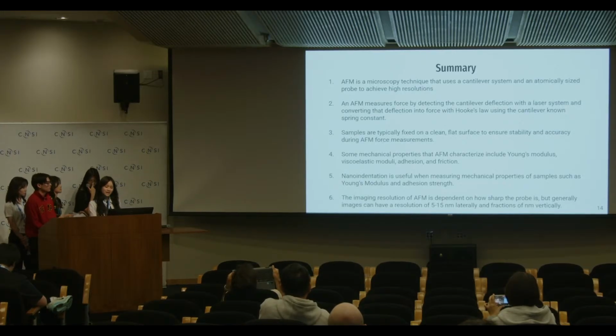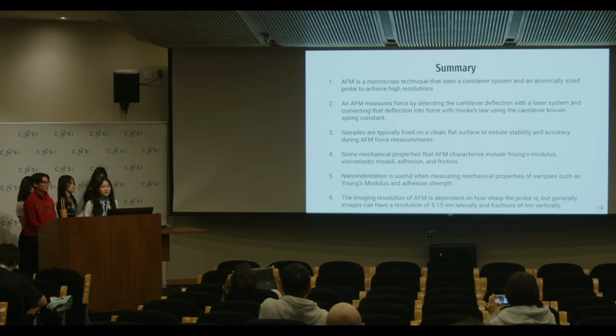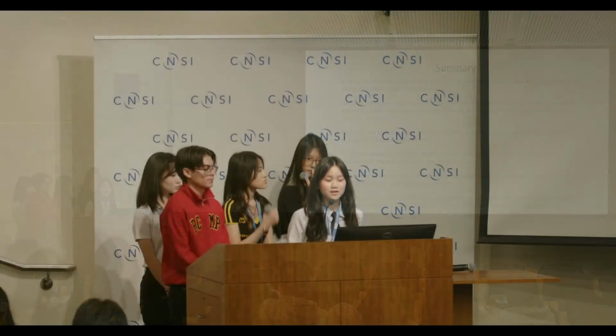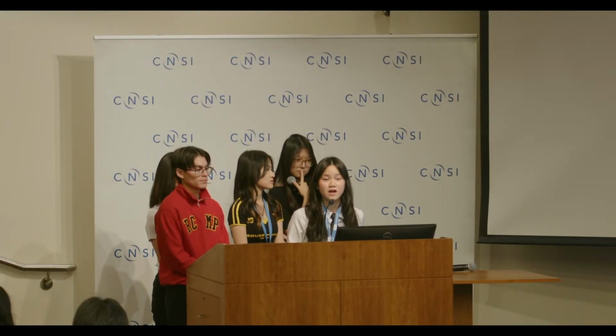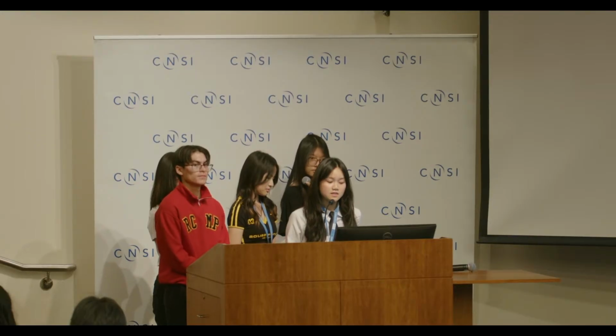This is a summary of everything we talked about today. First up is what AFM is, which is a microscopy technique that uses a cantilever system and an atomically sized probe to achieve high resolutions. An AFM measures force by detecting the cantilever deflection with a laser system and converting that deflection using Hooke's law. Then samples are typically fixed on a clean and flat surface to ensure stability and accuracy during AFM force measurements. Some mechanical properties that an AFM can characterize include Young's modulus, viscoelastic moduli, adhesion, and friction.